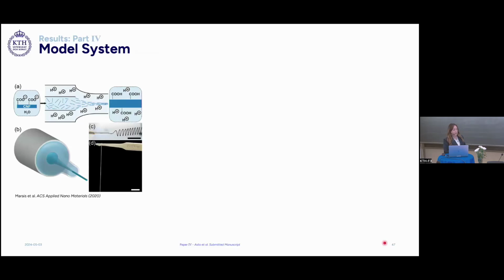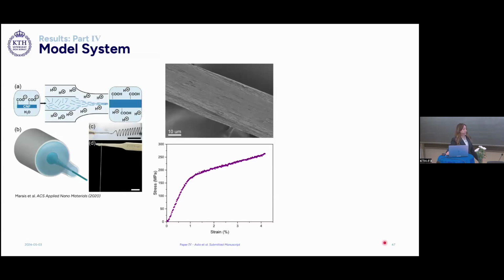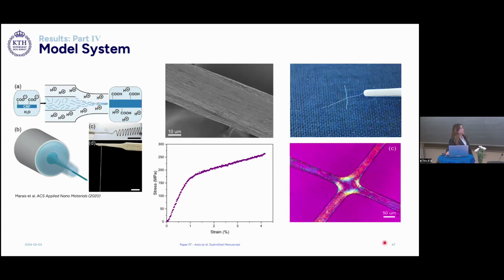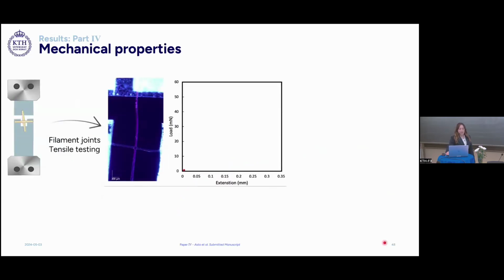First, in this work, we prepared CNF filaments by coaxial spinning of a CNF solution into hydrochloric acid solution. This technique was previously developed and was used to create our CNF filaments, which are then used to create a model joint by hot pressing 2 filaments together in a cross shape, mimicking a real fibre-fibre joint. The tensile strength of the filament joint was tested by doing tensile testing in the shear direction. The filaments were then LBL treated with PAH and HA.